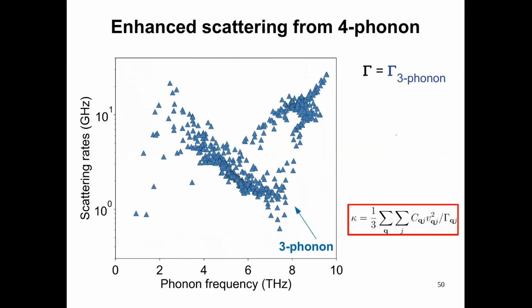To do this, let's go back to look at how the scattering rates compare between 3 phonon and 4 phonon processes. Once again, to refresh your memory, I'm showing the 3 phonon scattering rates of boron arsenide that I had calculated and shown earlier. You can see that these phonons have very low 3 phonon scattering rates, and because scattering rates occur in the denominator, these phonons contribute the largest to the overall thermal conductivity in the 3 phonon picture.